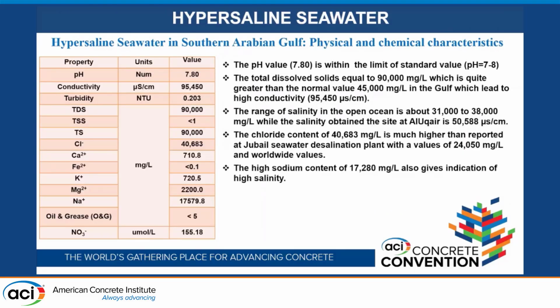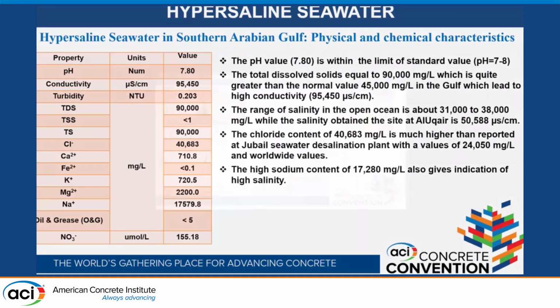But when we come to the southern part of the Arabian Gulf, from where we collected our seawater and where we wanted to see the effect of the higher side, you can see that the total dissolved solids is about 90,000 milligram per liter, which is quite greater than the normal value of 45,000 milligram per liter in the Gulf, which leads to high conductivity also. The salinity in the open ocean is generally about 31,000 to 38,000 milligram per liter, whereas the salinity obtained from the site at Al-Uqair is about 50,588. And the chloride content is almost double, 40,683. So we thought, let's look at the effect on the other extreme side of highly saline seawater. What is the effect on the concrete?